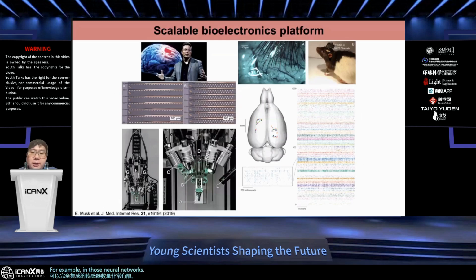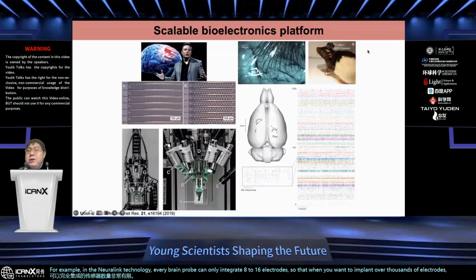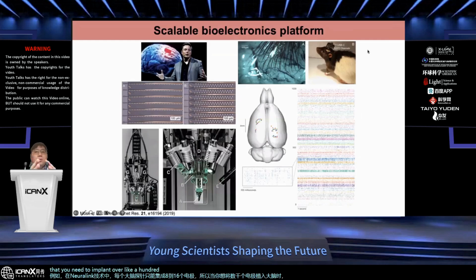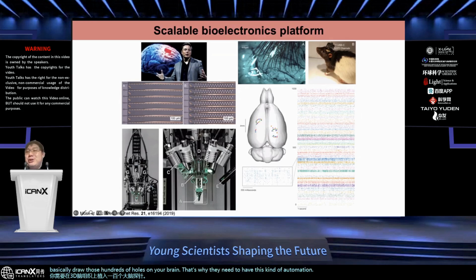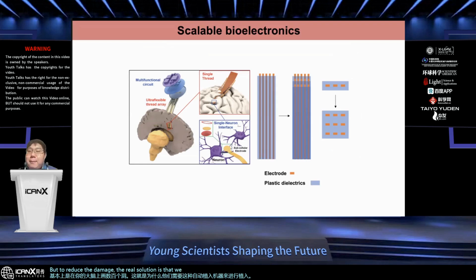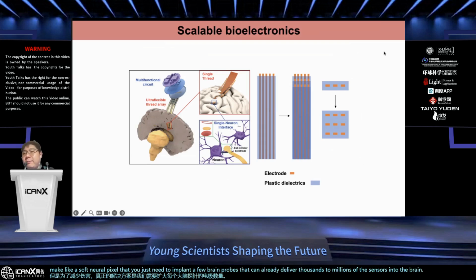For example, in Neuralink technology, every brain probe can only integrate 8 to 16 electrodes, so when you want to implant over thousands of electrodes into the brain, you need to implant over 100 brain probes across the 3D brain tissue. Basically, you draw hundreds of holes in your brain. That's why they need an automatic implantation machine. But to reduce the damage, the real solution is that we need to scale up the number of electrodes per brain probe. Make a soft neural pixel, so that you just need to implant a few brain probes that can already deliver thousands to millions of sensors into the brain without causing severe damage.